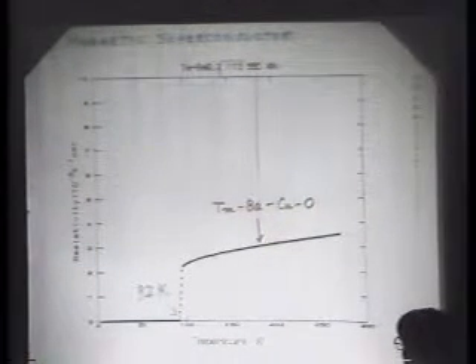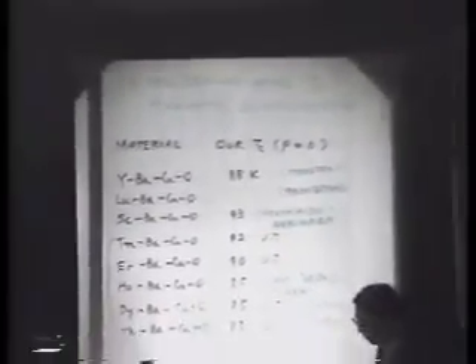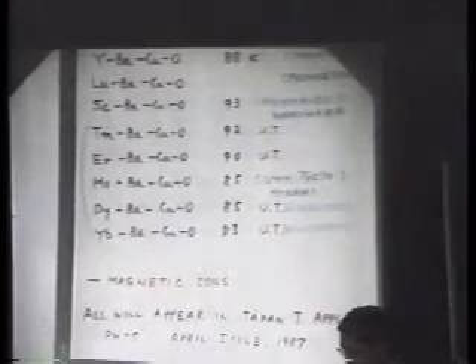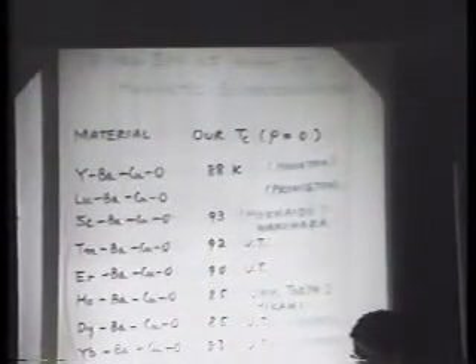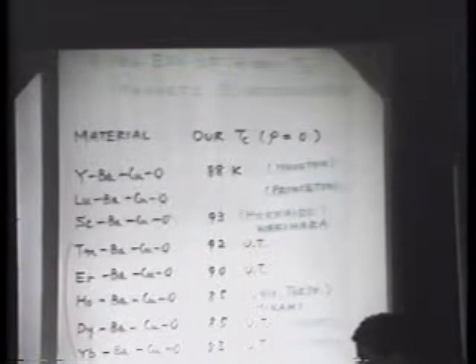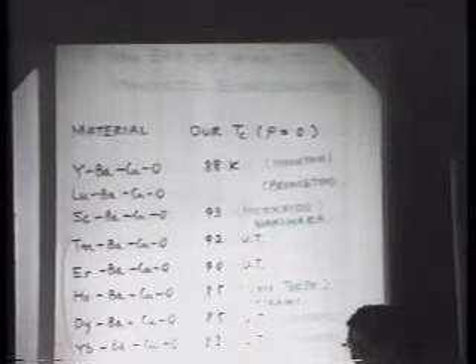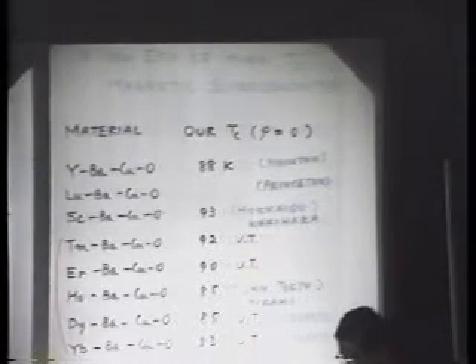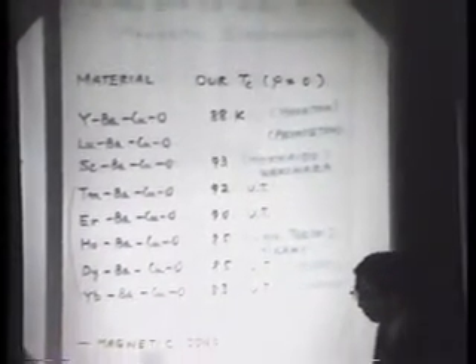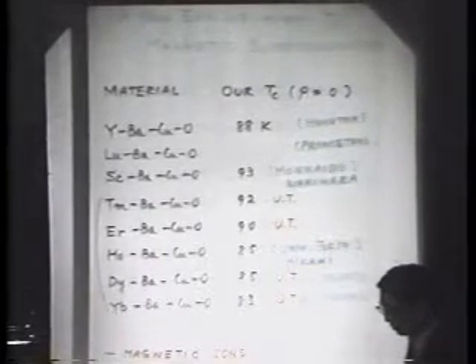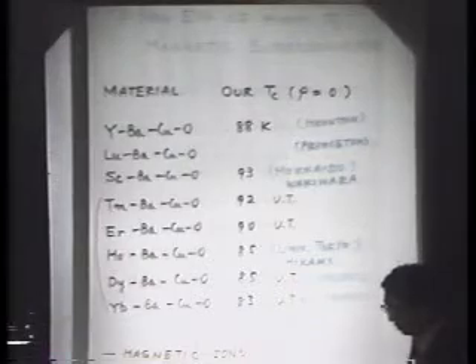It is very interesting. They have magnetism at temperatures beyond the critical temperature. So we can say that they are a new type of high TC superconductors, and at the same time, they are a new type of magnetic superconductors. It is surprising that the magnetic moments of these lanthanide elements do not affect the superconductivity at all. This fact may be related to the layer structure of these crystals. And this may provide a basis to clarify the electronic structure of these high TC superconducting materials, as well as the mechanism of superconductivity. Thank you.